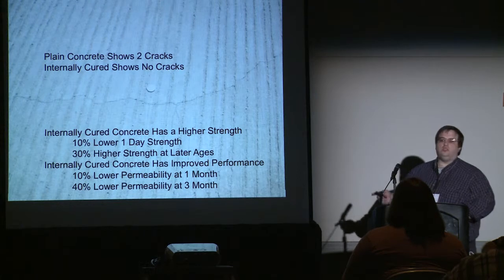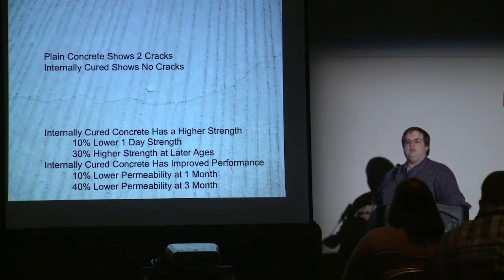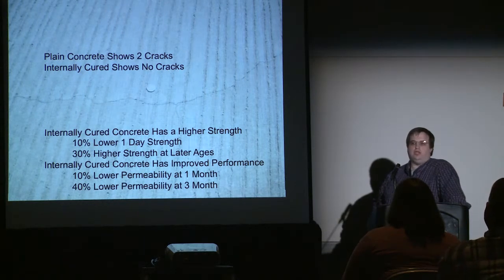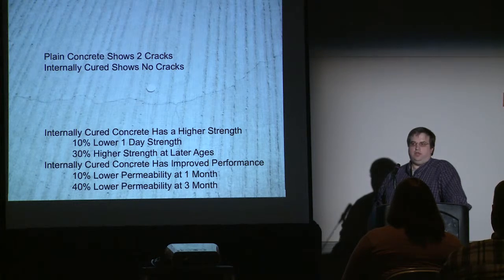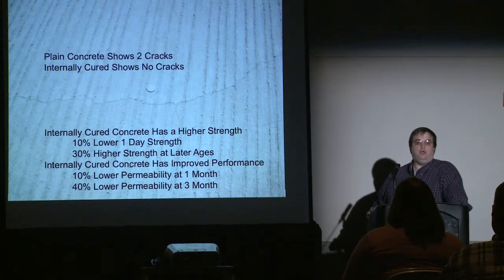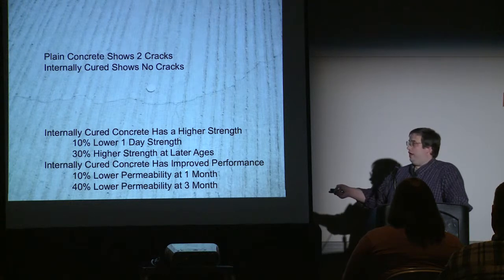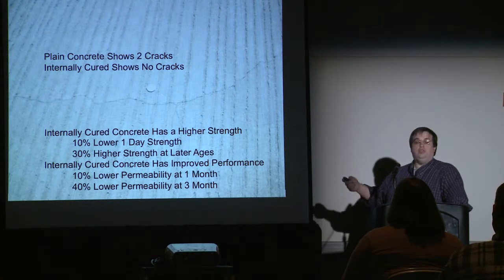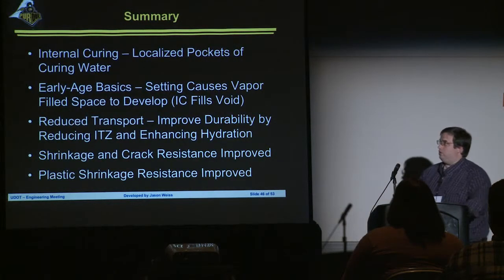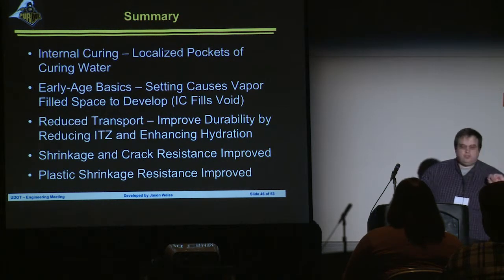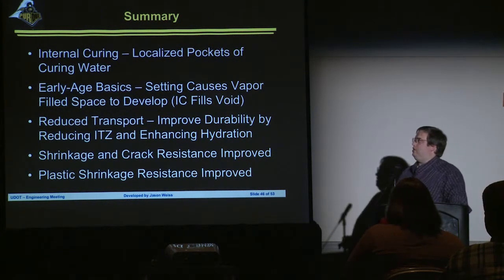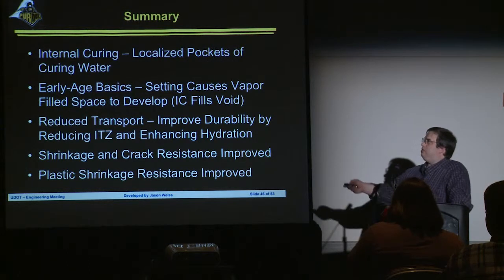We've been doing some studies where we're trying to measure corrosion rates. It was real easy to do for the restrained conventional decks. They started to corrode very quickly because they had cracks in them. The internally cured ones, 2 years later, we have no corrosion data, because they haven't started to corrode. You've got lower permeability, and you've prevented cracking inside of the overall system. So I want to give a brief summary, and then I'm going to hit some high points on some of the things that we're working on now to extend this a little bit.